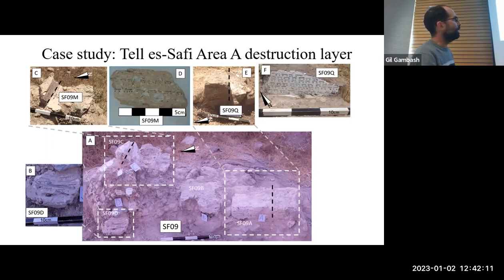And this brick here, I also cut it in half. You can see I removed one half and sampled the inside of it all the way through. This brick was completely falling apart. It was not hard and very hard to sample. I used non-magnetic glue to help me sample it. And you can see the plaster as well. So it was very challenging. I think this is because it wasn't fired to high enough temperatures like these, so it wasn't as hard. So I sampled the inside of it, and this is called Q.